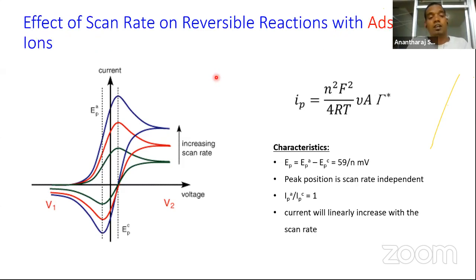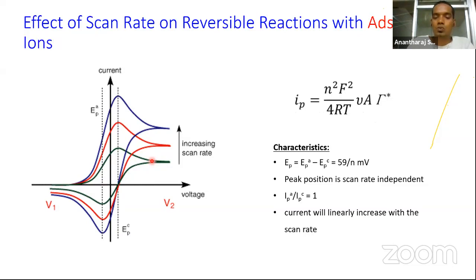If it doesn't exhibit a linear relationship, try plotting peak current against scan rate, and if you see a linear relationship between them, and you still have the peak-to-peak separation of 59 millivolt with increasing scan rate and the peak current ratio Ipa/Ipc of 1, we can say that the reaction is completely reversible but occurring via adsorbed species. So this is an example of the wonders you can do with a fundamental cyclic voltammogram, which many of us don't use in our studies. This is one thing that we can do with CV. So basically, you can differentiate the reaction by the mechanism by which it occurs.